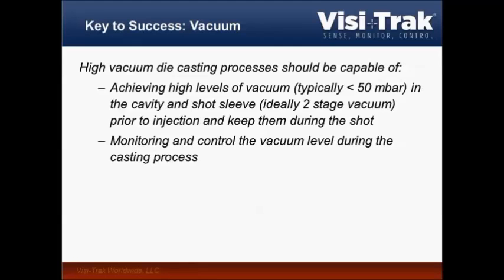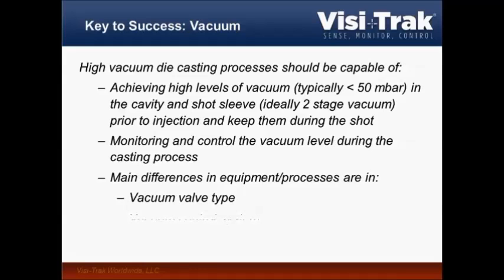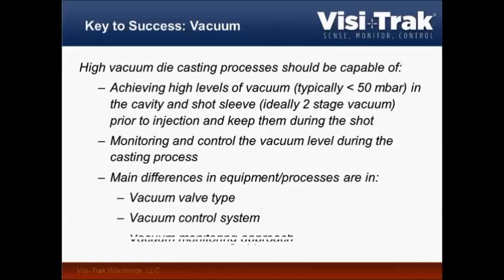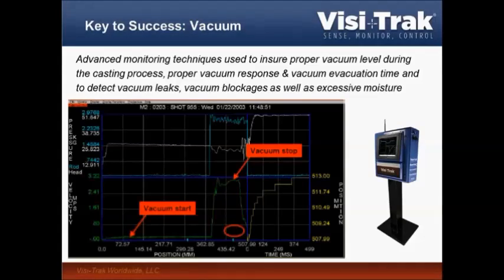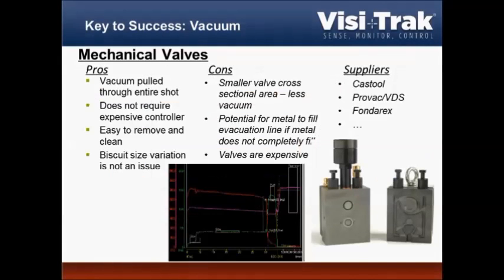Monitoring and controlling the vacuum level is key. The main differences that we find is really the vacuum valve type, the control system, and its monitoring approach. So you want to be able to basically put your vacuum curve on top of your shot profile, and depending on how you actuate your valve, your shot control system needs to be able to tell the valve when to close it and when to open it. We typically distinguish between mechanical and hydraulic valves.